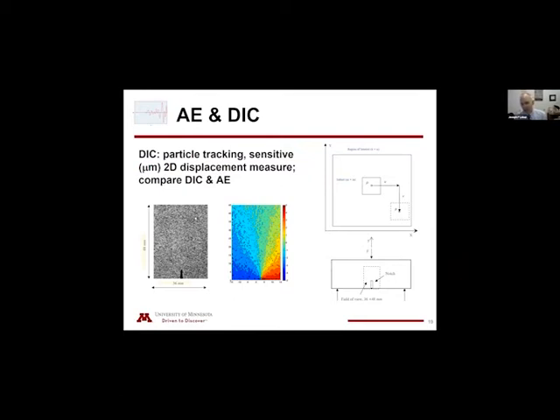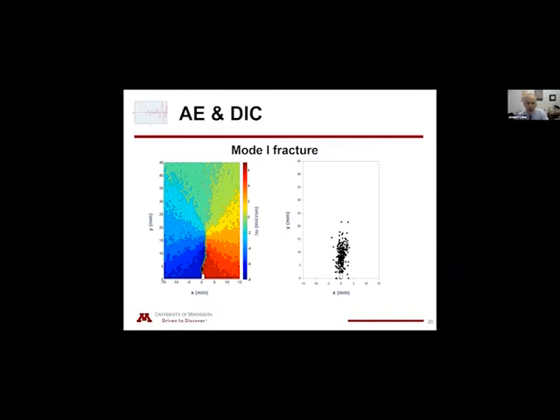Now the optics are trivial. That is, all you need is a digital camera. The processing of the data though is quite intense. In any case, DIC is particle tracking, and we use the data in a way that we plot fringes, that is contours of displacement. So the result in terms of the contours of displacement in the X direction indicate a fracture has formed and propagated quite a bit of distance. We started with a 2 millimeter notch, and we have a crack that has propagated to a position of roughly 18 millimeters in length, as indicated by the merging of the fringes, the contours, and it is well tracked by the acoustic emission locations that accompany these measurements.